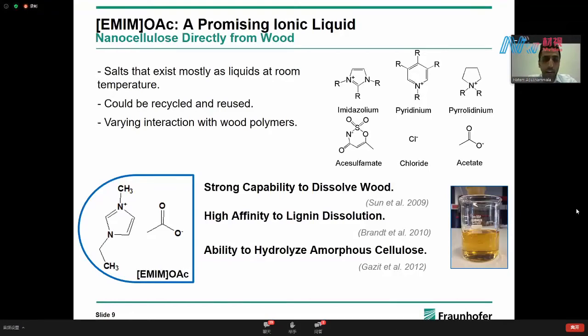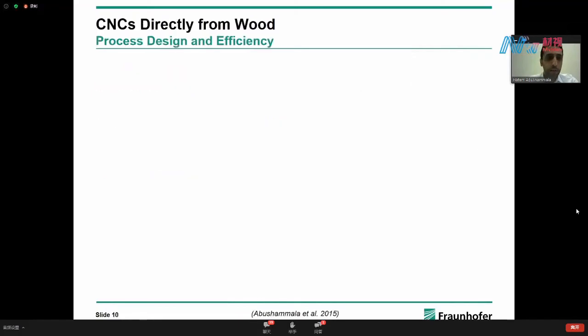For this purpose, I chose one certain ionic liquid, which is one of the cheapest ionic liquids. It's called 1-ethyl-3-methylimidazolium acetate. And this ionic liquid has been used to treat wood in general. So it can dissolve wood really efficiently, has high affinity to lignin, which is usually the most recalcitrant biopolymer in wood during pulping, and also has the ability to hydrolyze amorphous cellulose. So I developed my process based on that.